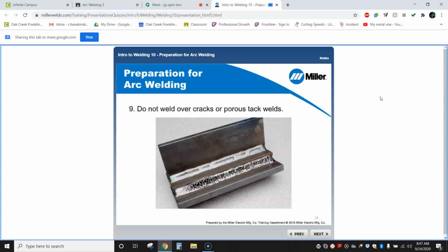Do not weld over cracks or porous tack welds. Defective tack welds should be removed prior to welding. So here we have some wormholes. Right here you can see these. Those are bad. If we were doing a multi-pass weld, we would have to grind all of that out and put another weld in without those. Because if you try to weld over these cracks or this ungodly porosity here, all you would do is have more cracks and more porosity on future welds.